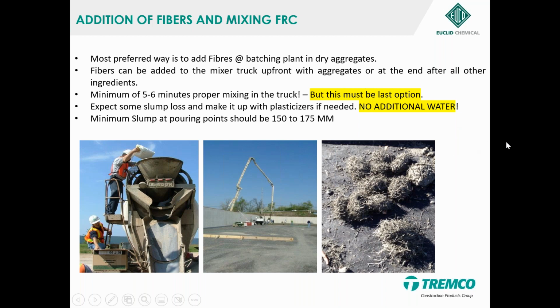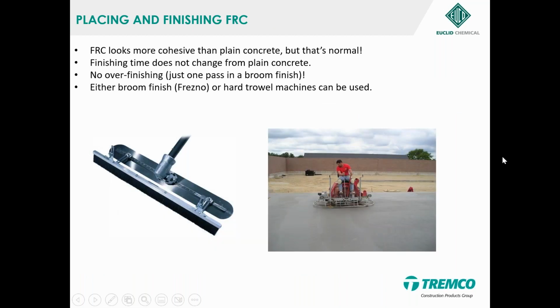Finishing is also one of the most important aspects of FRC. You should handle it like any other normal concrete. You should use the ride-on or the regular trowels at the right time. Otherwise, if you are a little bit late, then you may have a few of the fibers popping up. But the good part of polypropylene and polyethylene fibers, or the blend of it, is that even if it pops up, probably you can burn it off. So you don't have any issues, which can be a very big challenge when it comes to steel.